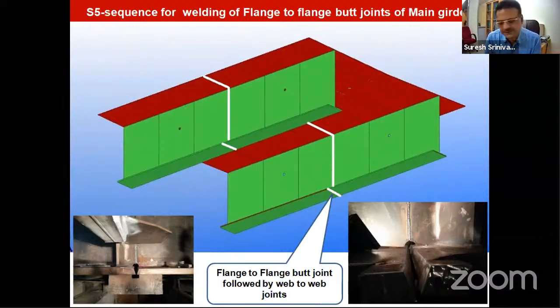So I felt that you are running into a brittle fracture condition in this case, and a lot of people resisted me. I produced a lot of evidence of how a brittle fracture can occur here, and especially how weld joints with notches can create a brittle fracture. So finally, they agreed with a lot of resistance.